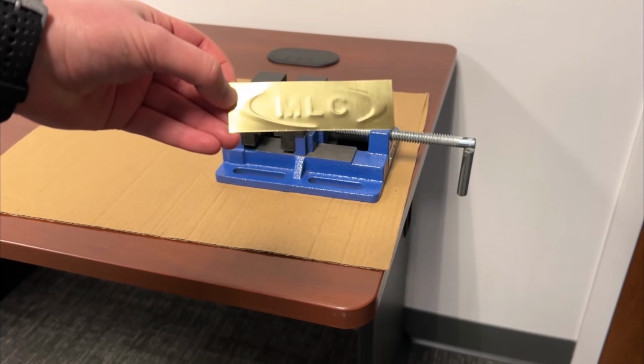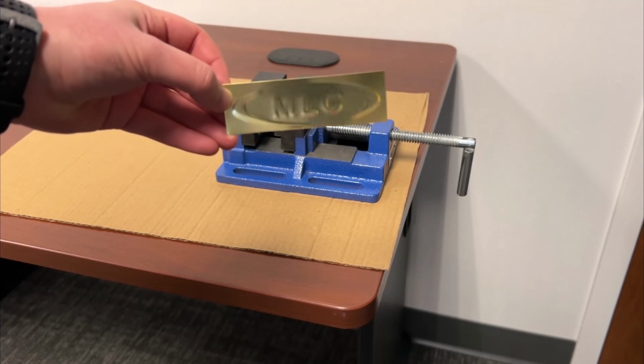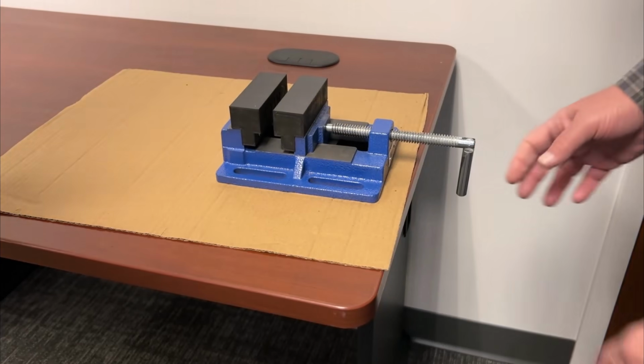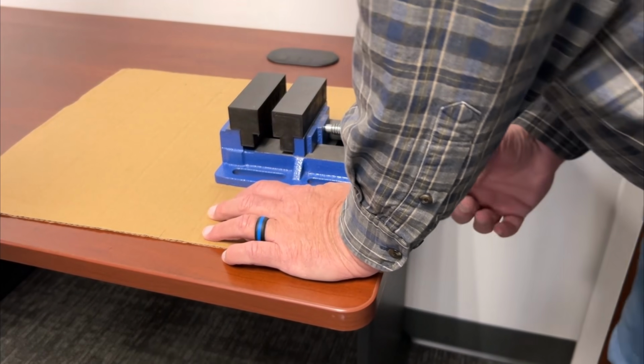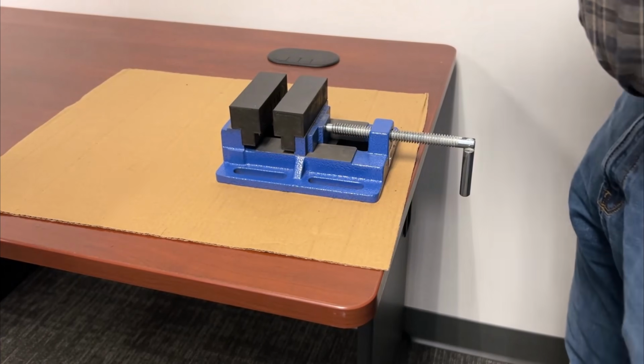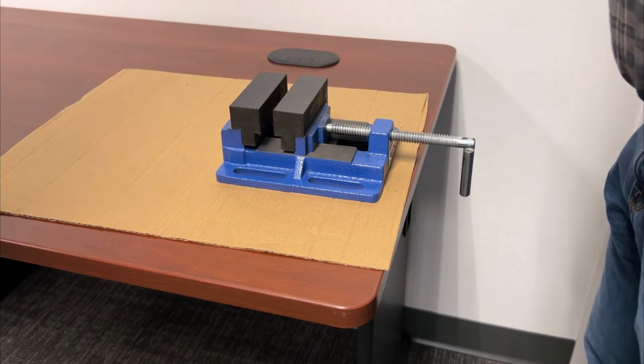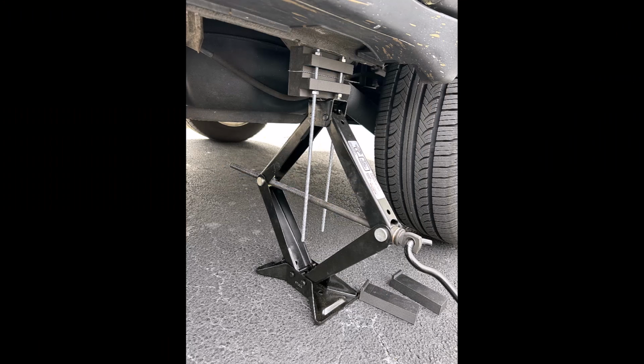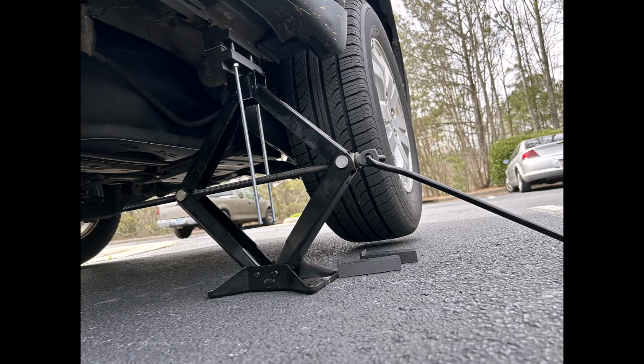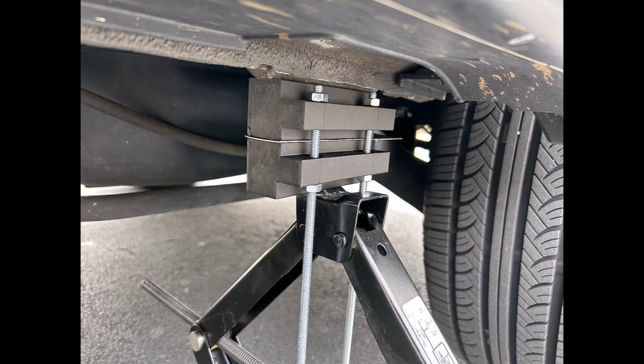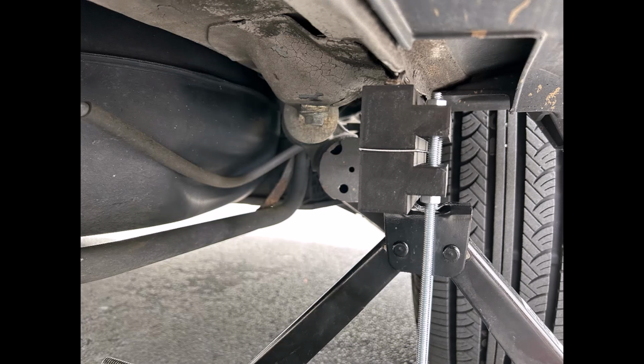Now, at this point, even with our new setup, we could not get crisp quality stamps with material thicker than 10 thousandths. In order to make it work, we needed a higher compressive force than either James or I are capable of producing with manual drive screw vises and clamps. Neither of us having access to a hydraulic or pneumatic press, I tried using my car's scissor jack and the weight of the car to get that much needed high tonnage force. This certainly did help a bit with that 25 thousandths thick aluminum, but we just needed more.